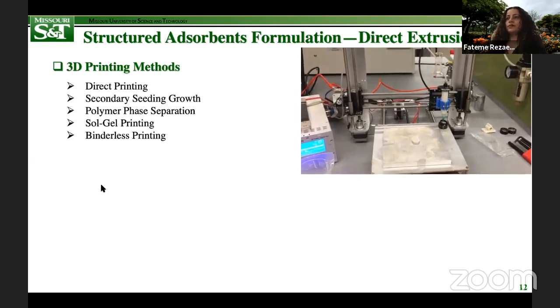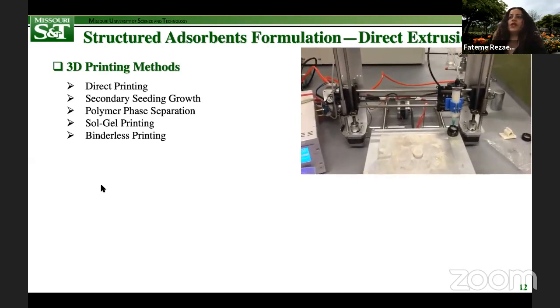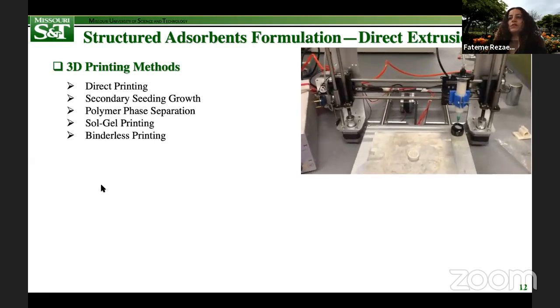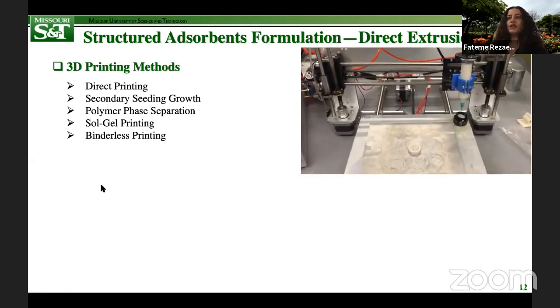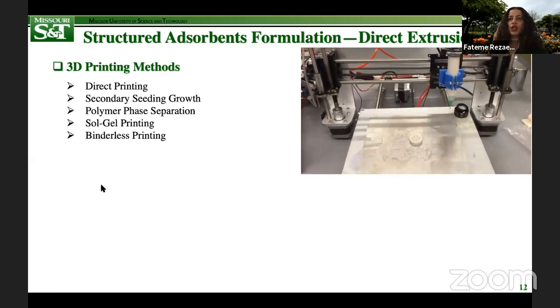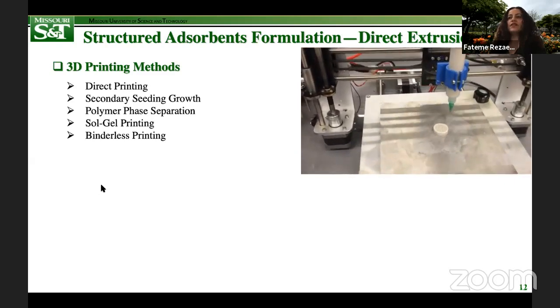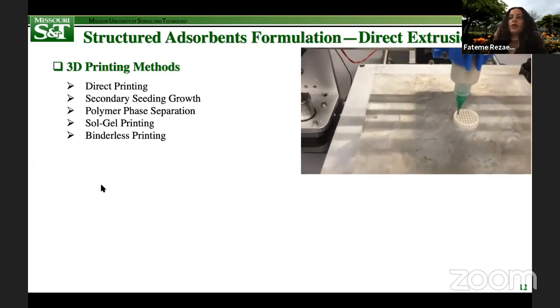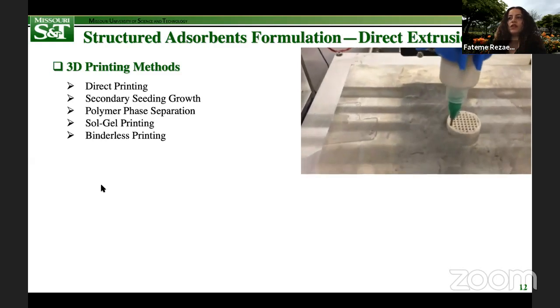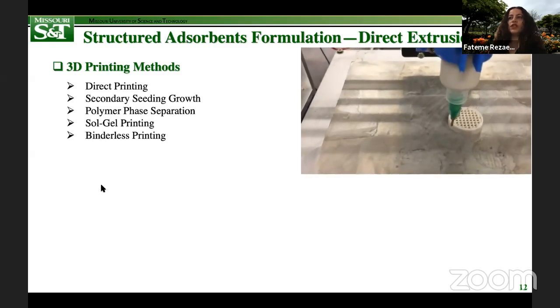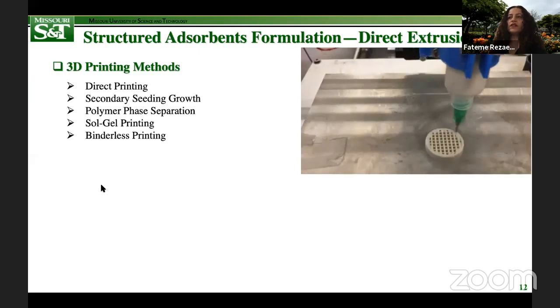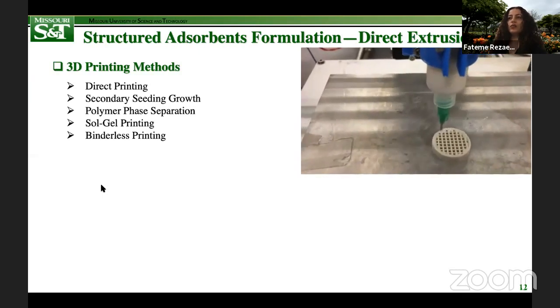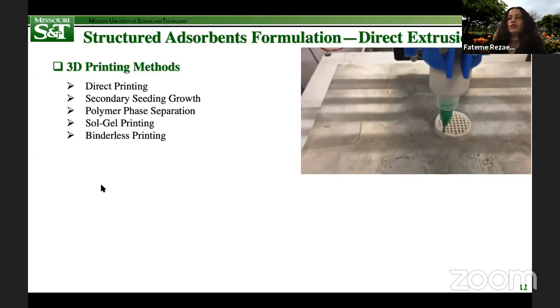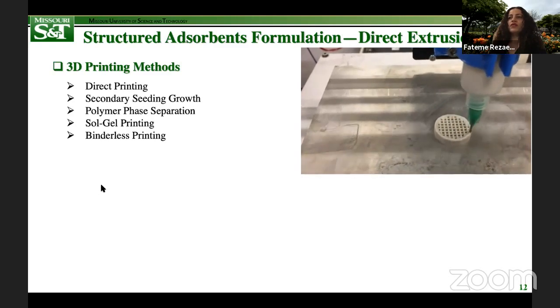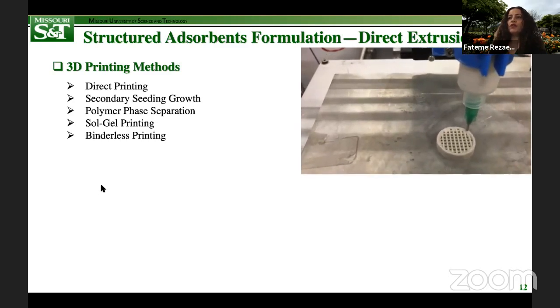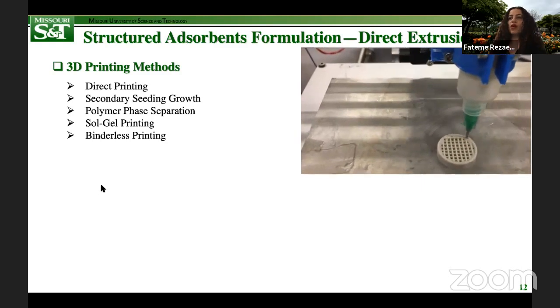So, direct printing, in which a pre-synthesized adsorbent is mixed with a suitable binding agent and printed into a desired shape. Then we have secondary seeding growth, in which a metal oxide is first printed into a desired configuration, let's say monolith, and then converted in situ to the adsorbent. This method is particularly applicable to MOFs and has been attempted for formulating MOFs into fibers or monoliths.